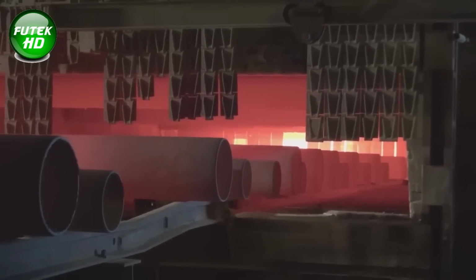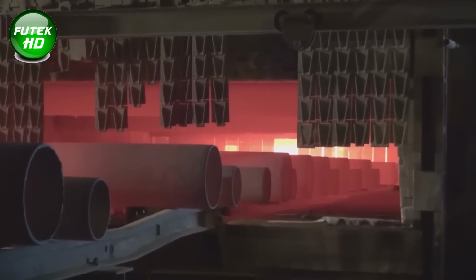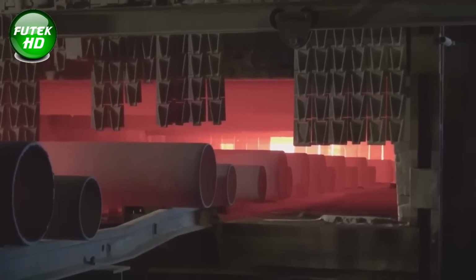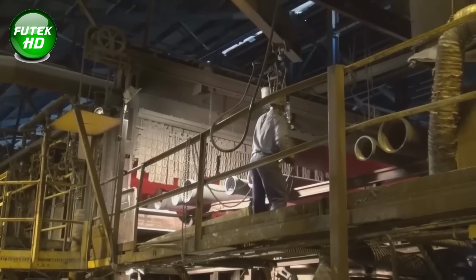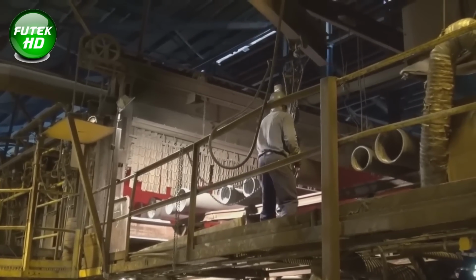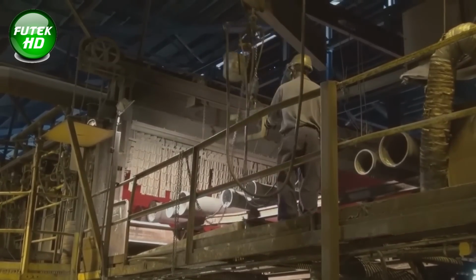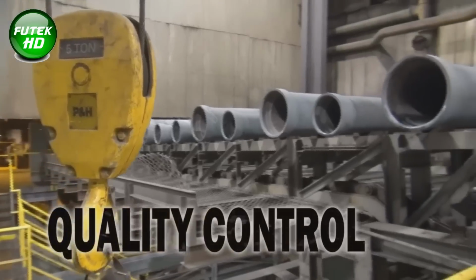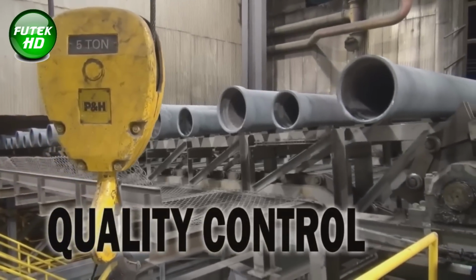As the pipes progress, the temperature gradually reduces to about 1,350 degrees Fahrenheit, 732 degrees Celsius in the cooling zone. The entire annealing cycle takes 35 to 45 minutes. This controlled heating and gradual cooling ensure the formation of spherical graphite nodules, essential for the pipe's ductility and strength.